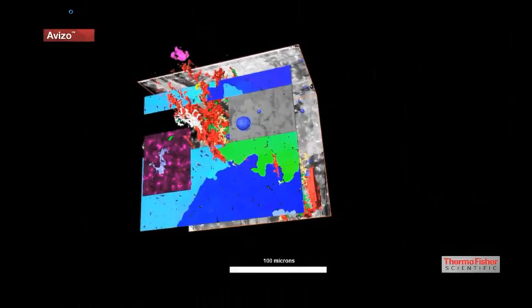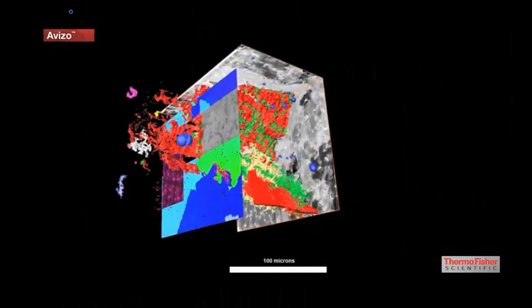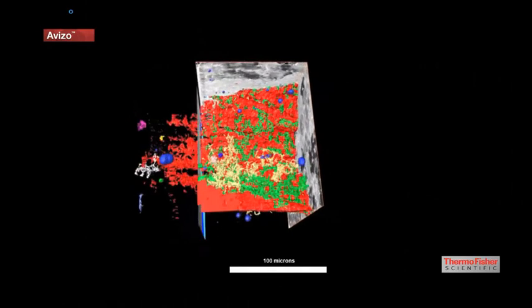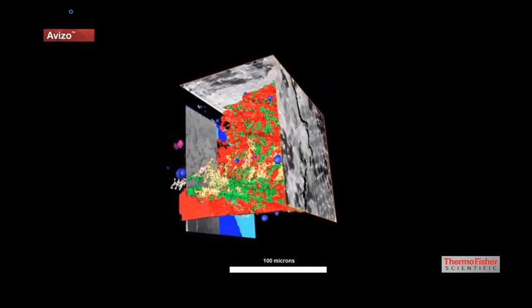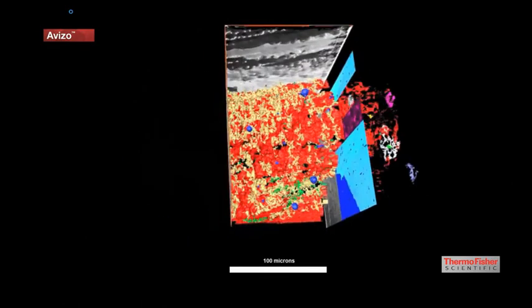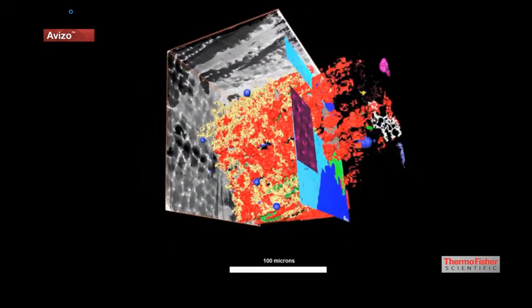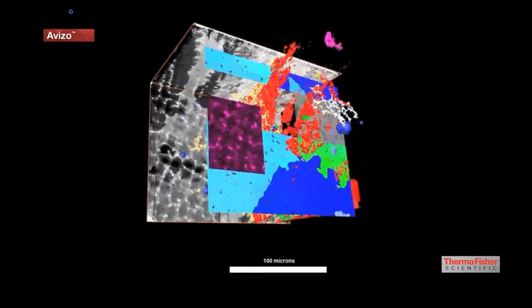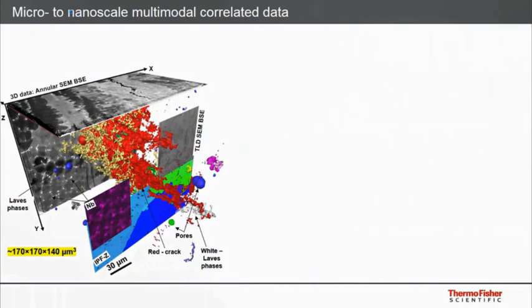At certain positions we collected EBSD and EDS maps. We found the cracks are formed on the grain boundaries in a region enriched with Laves phases. We also observed pores of different sizes and a region enriched with niobium. We didn't observe typical melt-pool structure but long columnar grains in the whole build.